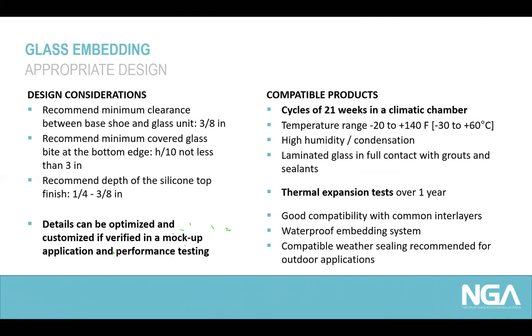We need to have compatible products, and the compatibility with the laminated glass interlayer was tested in artificial aging cycles over 21 weeks in a climatic chamber at a temperature range between -20 and +140 degrees Fahrenheit at high humidity and condensation. During that test phase, the laminated glass was in full contact with the grouts and with the sealants. We also performed thermal expansion tests with alternating cycles over more than 1 year to see if the flexibility of our grouting materials is good enough